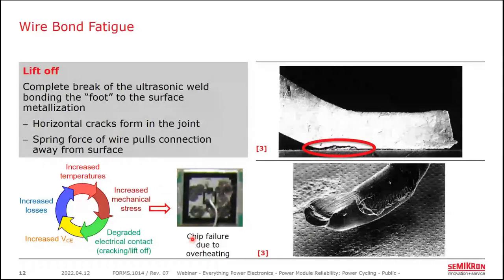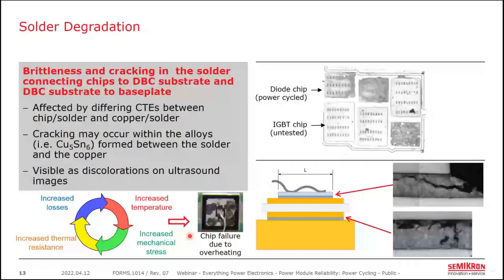The other major failure mode is in the solder layer itself, either between the chip and the DBC substrate, or between the DBC substrate and the base plate. So the solder can either crack along the interface to the copper, or the solder itself can break down. It sort of takes on a chalky consistency. And this is most noticeable in an ultrasonic image of the module, where deteriorated solder shows up as a contrasting color versus the consistent shadow that you would expect from a new module.